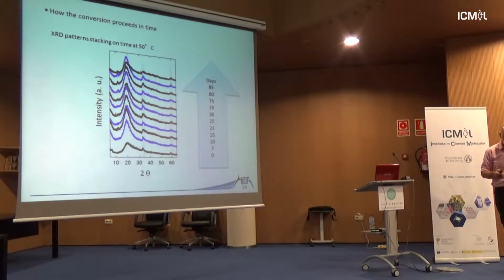First of all, just to show you that this is really the case, we recorded in time all these X-ray diagrams, from the starting point, 0 to 85 days, and of course it's dependent on the temperature. The more you heat, the less time you need to transform LSH to LDH. But you have a shift of these diffraction peaks, which is completely characteristic of your cell parameter, so the presence of two cations or one cation.